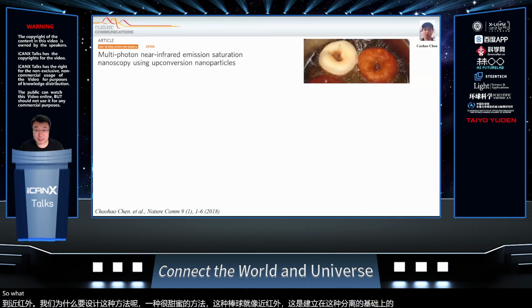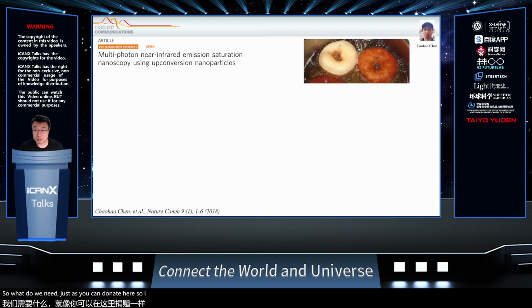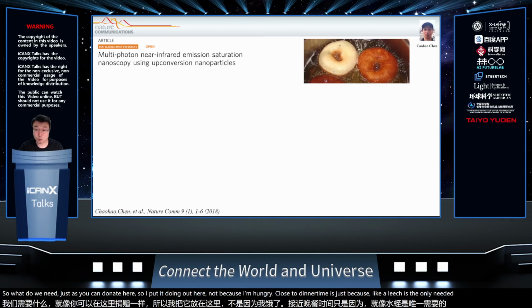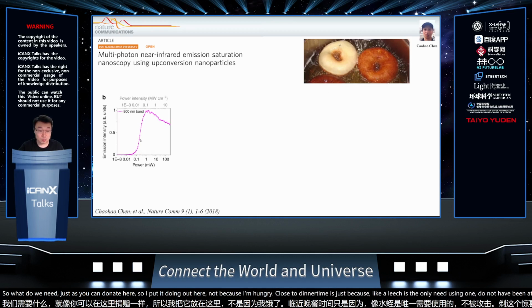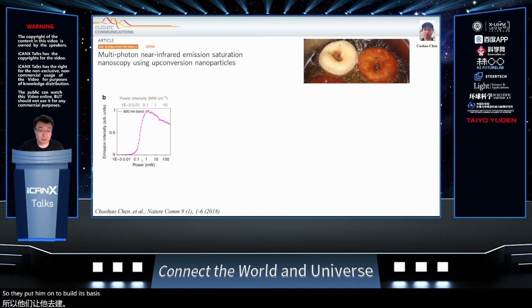So what we did is just use a donut here. I put a donut here, not because I'm hungry, close to dinner time. It's just because we only need one donut beam to achieve this super-resolution. We pretty much build it based on this power dependence. If you look at this, it's really nonlinear, and then has a beautiful saturation here. It means that if you further increase power beyond 1 milliwatt, you can't see much intensity change.